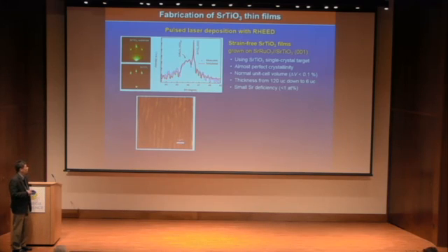We measured the stoichiometry by RBS and then WDS, and the composition is almost 1-to-1 within the experimental error. So that's less than 1% of small strontium vacancies. And that creates enough nanopolar regions and creates the emergence of ferroelectricity. And you see that this is strontium ruthenate and this is the thickness oscillation.